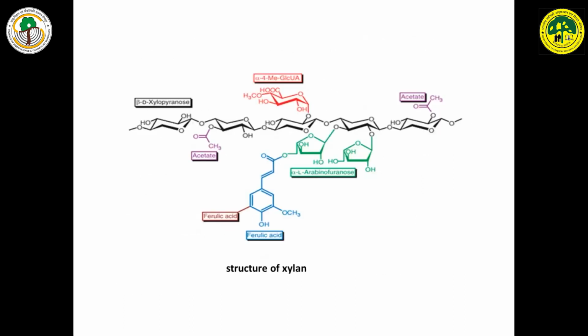Here in this structure, it is the aromatic ester, ferulic acid. So that aromatic ester is the component of lignin. So xylan is the material of the hemicellulose polymer, which is again bonded to lignin also. So individually, any component is not present. That means hemicellulose and lignin components are not separated. They are bound together by bonds like the ester linkage here in the xylan. The ester linkage is found in between the lignin material and the hemicellulosic material, that is xylan.